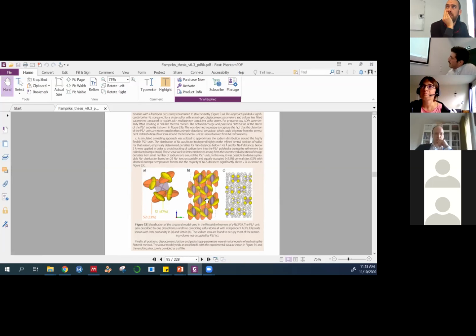These are ellipsoids at 50% occupation. Imagine if I put them at 90%, which is normal to present such things. And for the sodium atoms, yes, there are a lot of positions, but it's because, as seen in the molecular dynamics, the sodium is everywhere. If you look at the Fourier transform electronic density, there's really no sign of any stable atomic position anywhere. So this is just a way to smear electronic density everywhere that is not a PS4. I hope I'm capturing some point. Maybe you want to direct me more to what else you might be interested in.